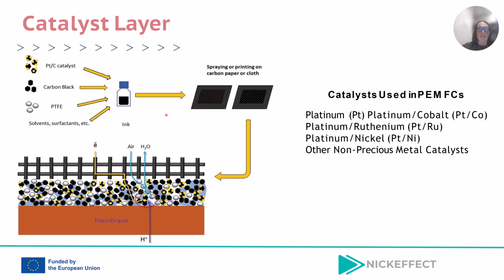Here you can see the structure. Air and water enter from the top, protons move through the membrane from the anode side, and the catalyst layer facilitates the reaction between oxygen and protons to form water. Different types of catalysts can be used depending on the application and performance requirements. Some common ones include platinum, platinum cobalt, platinum ruthenium, platinum nickel, and also non-precious metal catalysts, which are being explored for cost reduction.